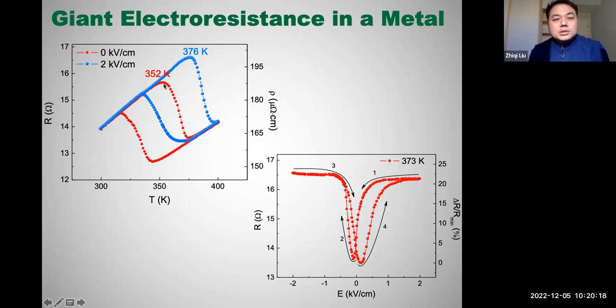At a 0 electric field, the transition temperature is around 350 K. But when you apply an electric field that generates a tiny piezoelectric strain, the phase transition temperature is tuned up to 370 K. So around the phase transition temperature, at a 0 electric field, previously it was already in the ferromagnetic phase. But when you apply an electric field or a piezoelectric strain, this thin film is tuned into an antiferromagnetic phase.